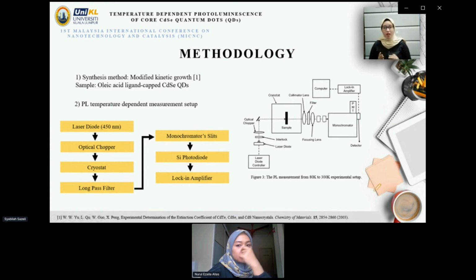The cadmium selenide was excited using an unpolarized 405 nanometer laser diode onto the quartz substrates, and then PL spectra were gained. The emitted PL from the cadmium selenide film is collected and collimated onto the cryostat window before being focused onto the monochromator slits, and then detected by the silicon photodiode. A long pass filter eliminates any 405 nanometer light. Lock-in detection is allowed due to the modulation of the laser beam. Thus, all the PL spectra were rectified for the system spectral response.